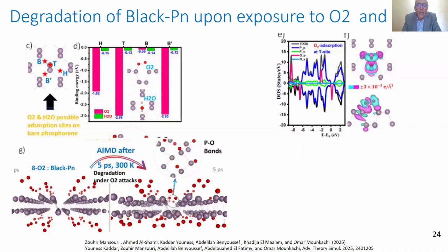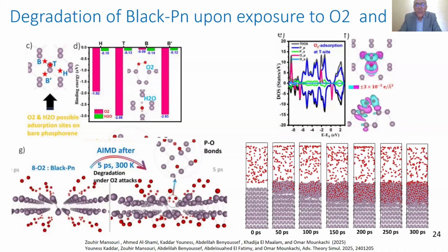But if we look at black phosphorus, we see the same behavior for many layers of phosphorene. We can see that with increasing time during the simulation, oxygen makes bonds with phosphorene and penetrates deep into the black phosphorus. That means that the material is not stable in the presence of oxygen. And how to make it more stable?